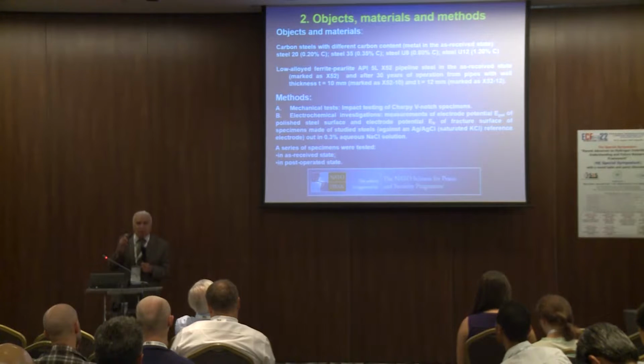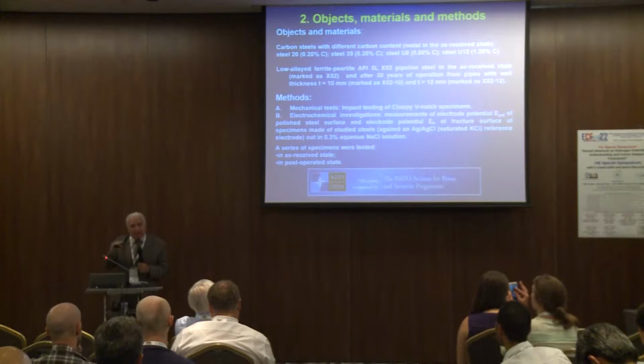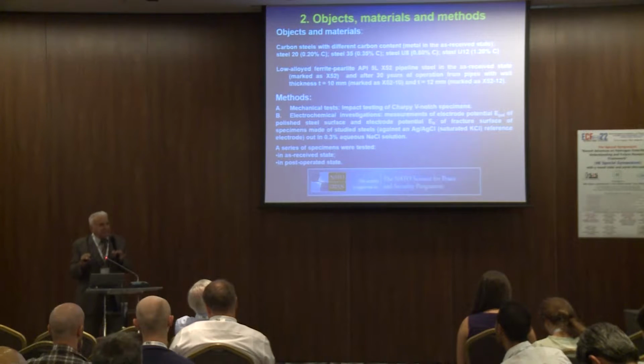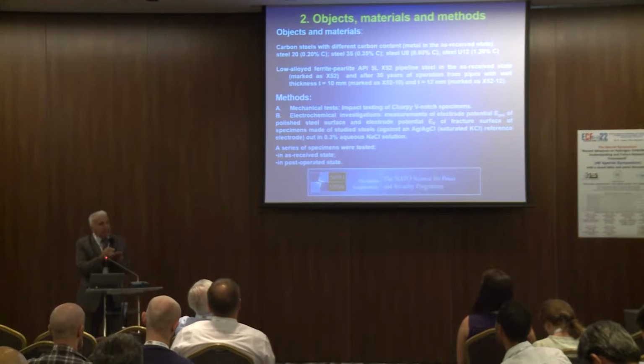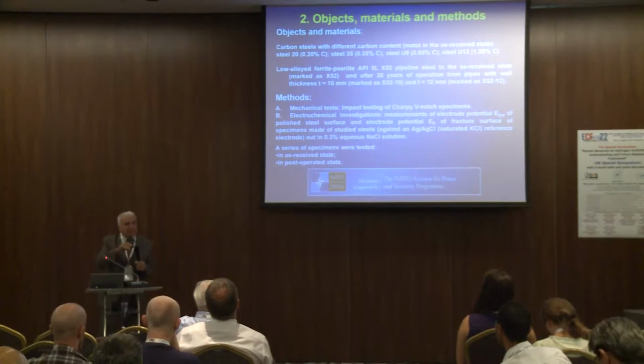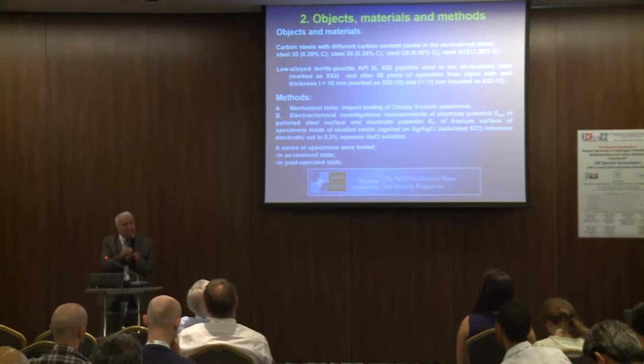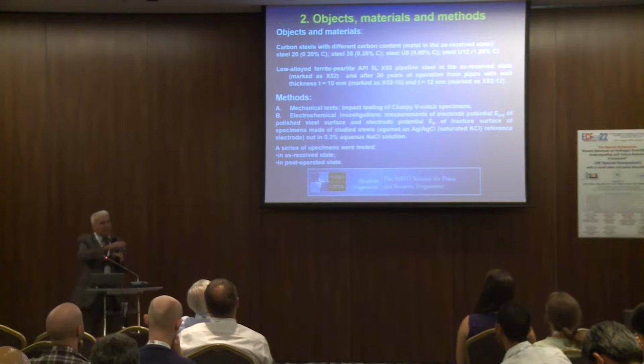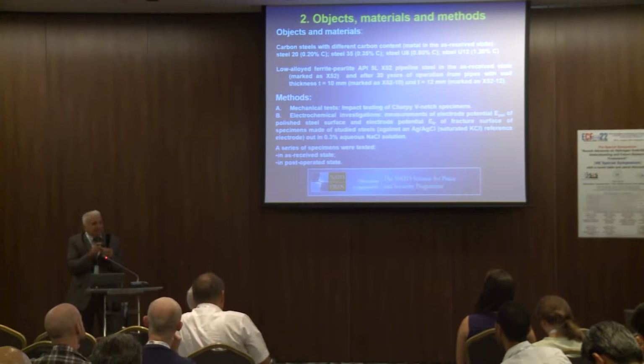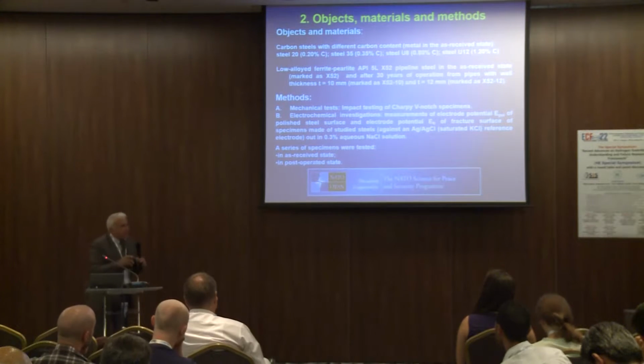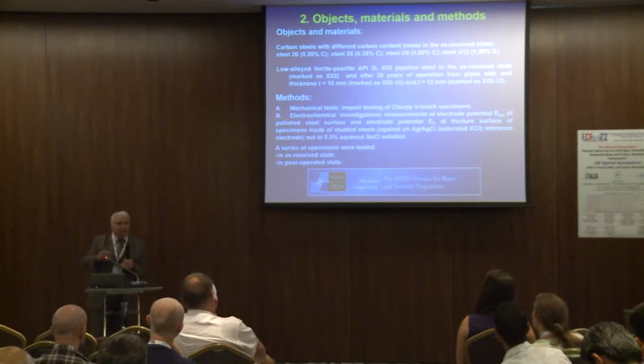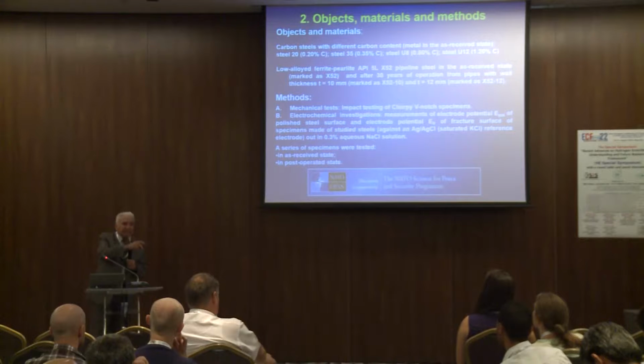In this work, we propose to use not electrochemical properties of polished metal, but of the fracture surface. Why? It is known that the process of degradation occurs non-uniformly, and therefore a fracture crack propagates via local sites with minimum energy for fracture. It means maximum level of degradation. So we expect that the fracture surface concentrates the most measurable changes of metal which led to brittle fracture. It is the philosophy of our approach: to measure electrochemical properties of the fracture surface of specimens after a brittle fracture resistance test, for example, impact strength, as in this work.